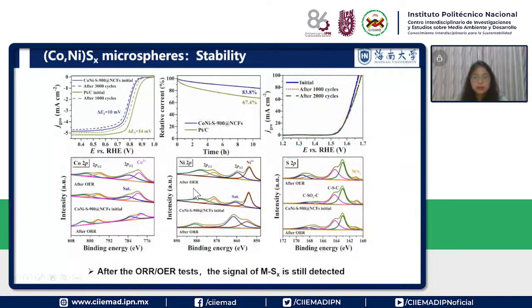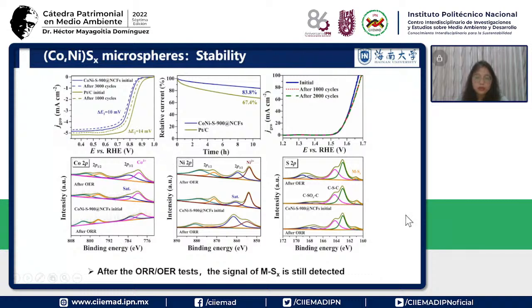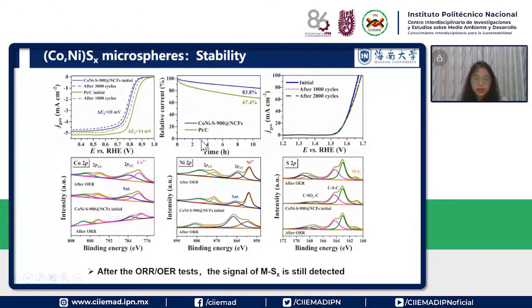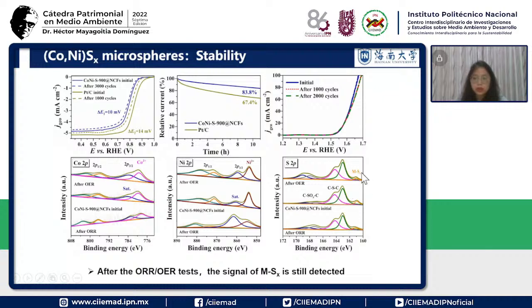And then for these cobalt nickel sulfide microspheres, we test their stability, and after the stability test, we want to know about the surface electron structure of these materials. We can see after the ORR and the OER test, the signal for the metal and the sulfur is still detected.